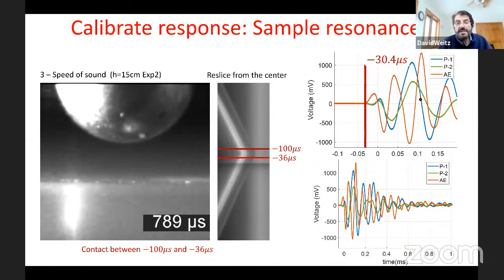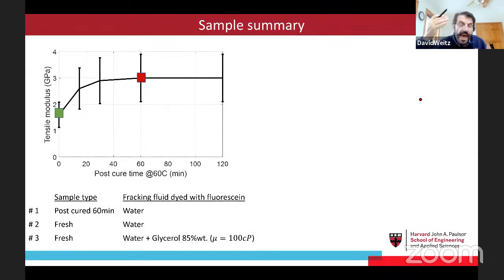And this is what you would expect, that as you have some localized crack, some localized noise somewhere in the sample, you'll get a little ringing, you'll excite some response of the sample. We should be able to filter the signal from that, and then watch what happens as the crack propagates through the sample. And so let me show you some preliminary results along this line.